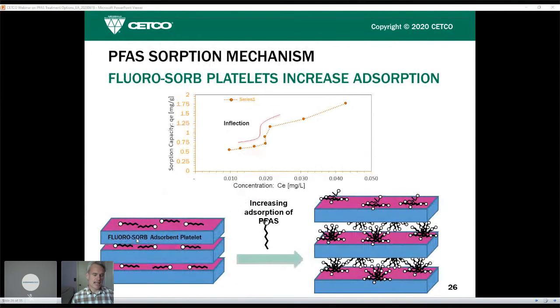So Mike and CETCO have been doing some work to try to evaluate the nature of the high capacity that's often seen for FLUORO-SORB for PFAS removal. And he did talk a little bit about this when he was presenting adsorption isotherm results. But here we have the solid phase concentration or sorption capacity on the y-axis as a function of the equilibrium, aqueous phase concentration. And typically for isotherm experiments, you do see a leveling out of the solid phase concentration or sorption capacity as you increase the aqueous phase concentration of any solute. What's interesting with FLUORO-SORB is you typically don't see this, and you can see this inflection point that indicates there's some increasing capacity as you load PFAS onto FLUORO-SORB, which is hypothesized to be due to the platelet structure and the fact that these platelets can expand as the FLUORO-SORB starts to absorb PFAS. Next slide.